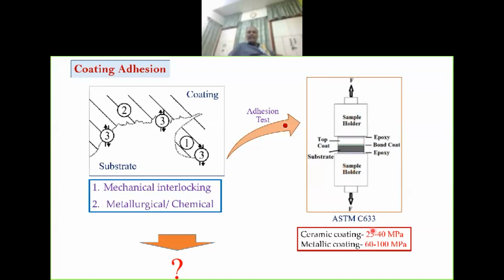If the coating breaks, glue is usually stronger. Now very strong glues are available in the market. If the ceramic coating goes up to 25 to 40 MPa, it's okay. For metallic, we got to 60 to 100 MPa. It's okay. As long as it works, it serves the purpose. We do not get into it. Why? One explanation is that the interface between the coating and substrate is too thin. It's difficult to investigate. We carried out a small investigation somewhere.